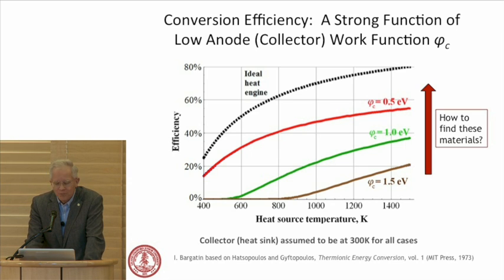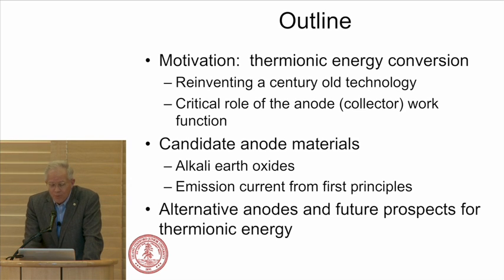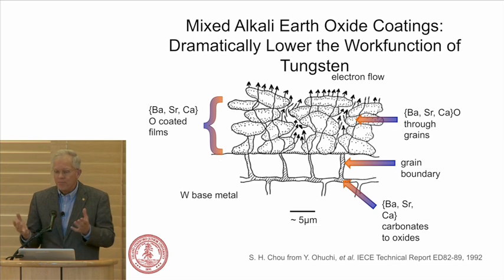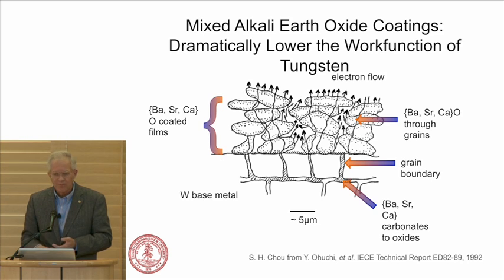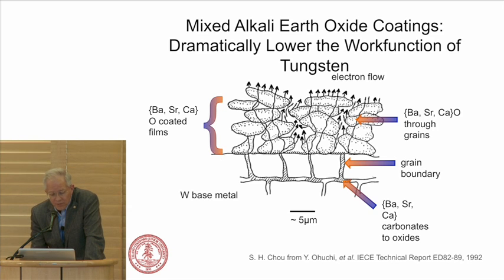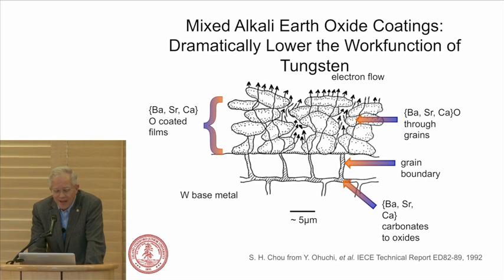So in any case, how do we find these materials? And now we get to this particular critically important GCEP grant because, in fact, there's a whole industry with electron sources, SEMs, electron beam lithography, instruments of all kinds, and these are often made with a tungsten base metal, typically not crystalline, coated with a mixed oxide, alkali earths, barium, strontium, calcium, sort of mixed up in a mortar and pestle kind of fashion in some cases, and deposited in interesting ways with migration into the grain boundaries, and ultimately a very complex process leading to electron emission and low effective work function.